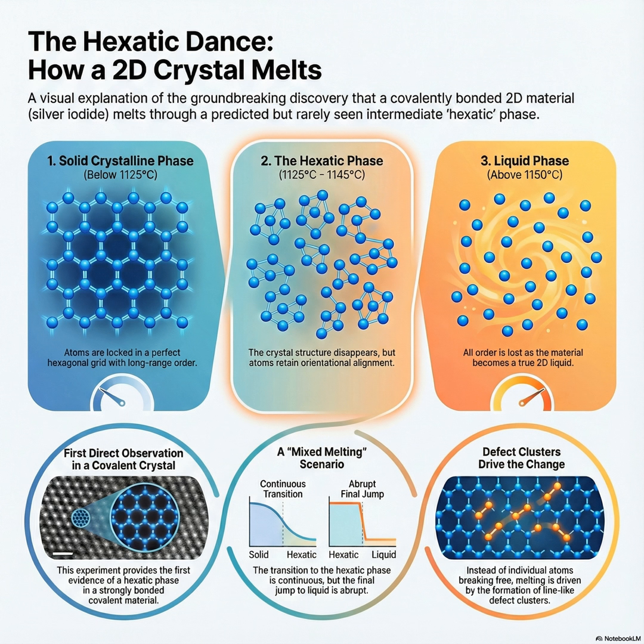But if you just heat up a 2D sheet of it, wouldn't it just instantly crumple into its 3D form? It absolutely would. The moment you thin a material, it wants to minimize its surface energy, which means changing its structure. So to prevent this, the research team had to do something pretty remarkable. What was that? They encapsulated the single atomic layer of silver iodide in multi-layer graphene. Whoa! So they made a microscopic sandwich. That's a perfect way to put it.